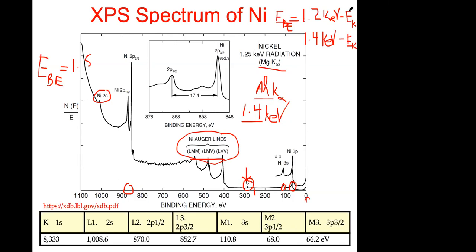If this is the same and this is higher, then the binding energy is higher. So this difference will be higher than this one, and you'll have a higher binding energy, meaning these peaks will move in this direction. If they moved in that direction, that means they are Auger. They're going to go higher for aluminum than for magnesium, because magnesium is 1.2 and aluminum is 1.4.